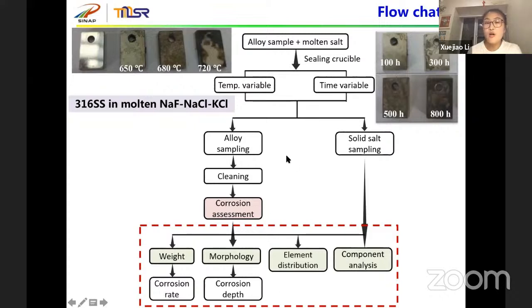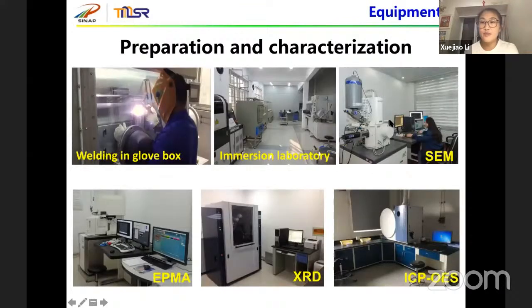Both components of the alloy and solid salt are analyzed by the following instruments. For example, the SEM is used to observe the surface and cross-sectional morphologies. The EPMA is used to analyze the element distributions, and the XRD is to test the crystal phases of the alloy. The ICP-OES is to detect the ionic concentrations of molten salts.